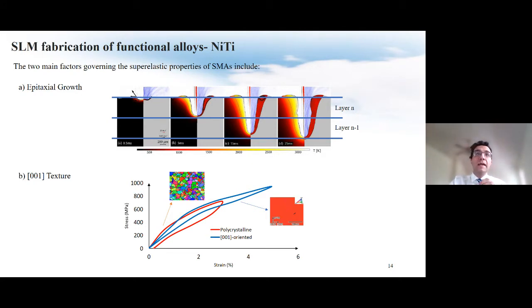In regard to the texture, it is well known that the presence of 001 texture can significantly improve the superelasticity when compared with polycrystalline structure. As you can see here in this figure, the level of strain recovery is about 5% for single crystal conventional material, while it is only 3% for the same material in the polycrystalline mode, for the conventional, again, fabricated part of nickel titanium.